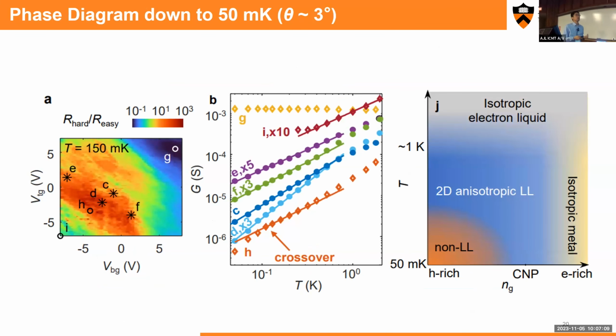And also we can show the phase diagram of this system. We found that at the very, very hole-doped region like here, it actually deviates from the Luttinger-Liquid behavior, which I say is the power law dependence. It deviates from the power law at the very, very low, hole-rich region. And then near the charge neutrality, we can still get the power law down to 50 millikelvin. And this is the fine tuning of such a system, and we can still maintain the Luttinger-Liquid physics. And if you keep doping it, it's going to be the isotropic area.